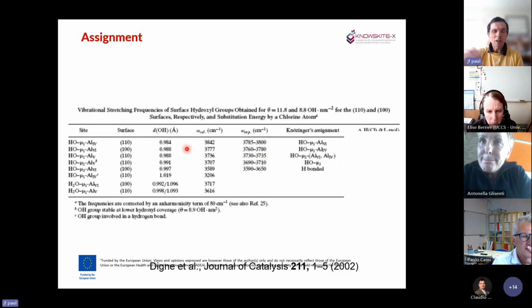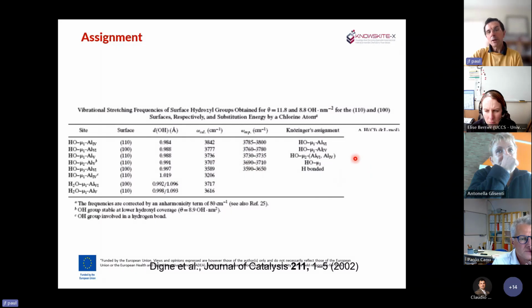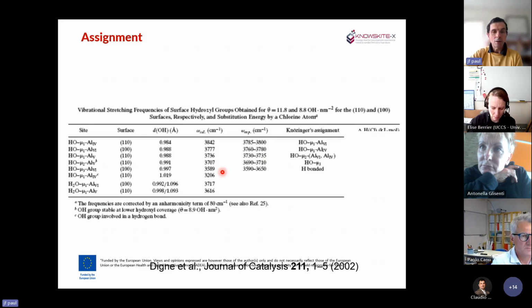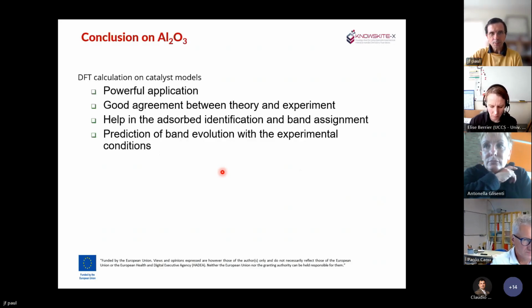And thanks to the calculation, you also know exactly on which type of surface the molecule is adsorbed, and since the two surfaces are not equivalent, their properties may not be fully equivalent. So by considering the intensity of the different types of vibration, it also gives you a way to have an idea of the shape of the particles that you have created when you synthesize your particle. So it's quite good and it works almost correctly.